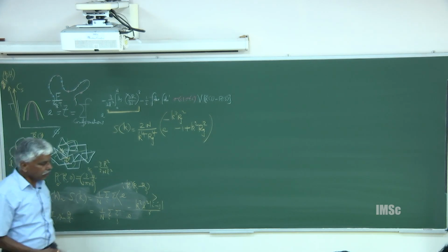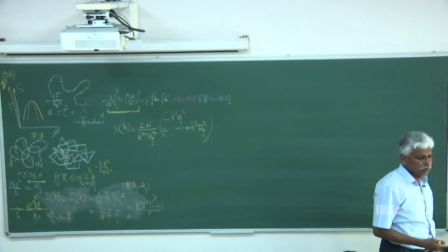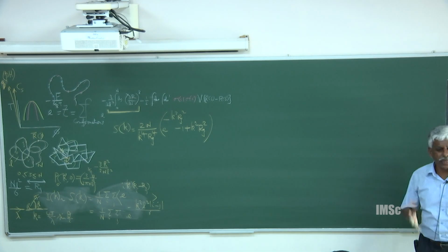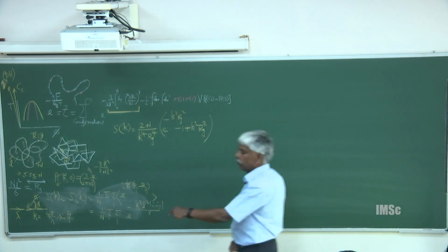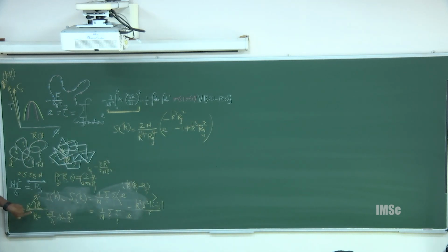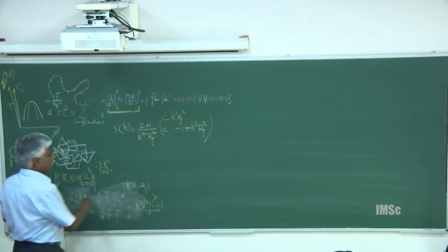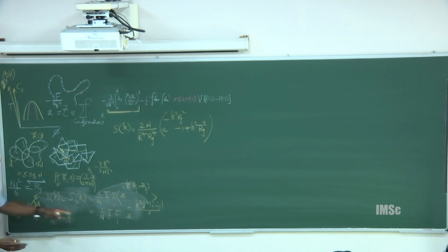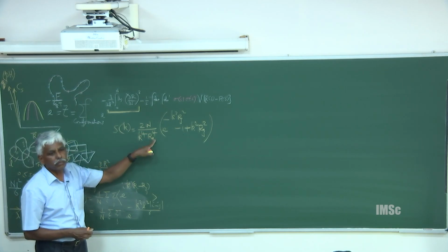And this, in fact, makes the principle of experimentation. The way biopolymers or synthetic polymers are characterized is using that expression. That is the theory, and this is the experiment. Even Debye was also a great experimentalist. So, he would do this experiment and this theory, match the two and then determine everything. He will determine the molar mass of the polymer, how big the number of monomers is. He will also figure out Rg, because N appears here, Rg appears here.